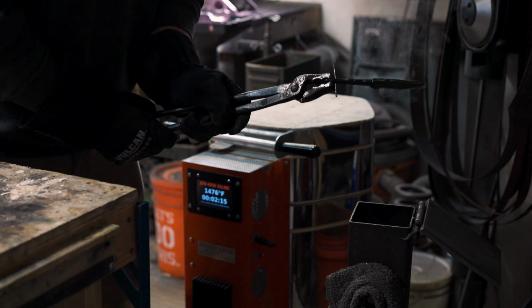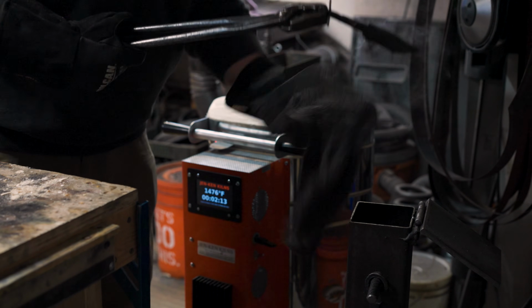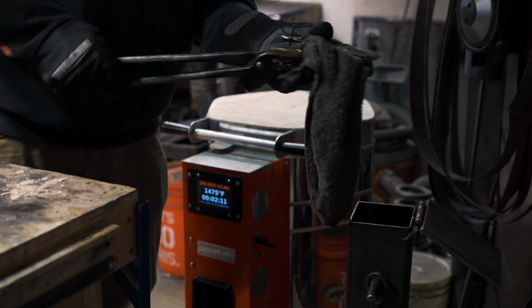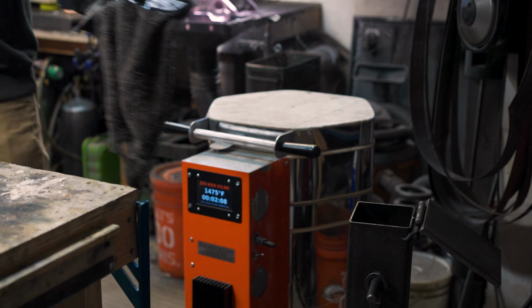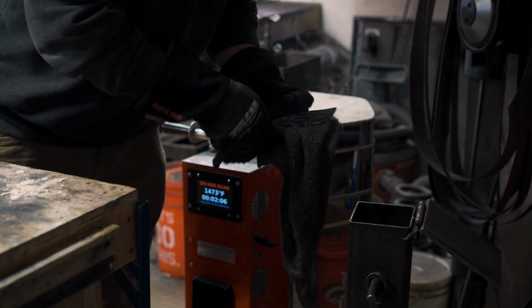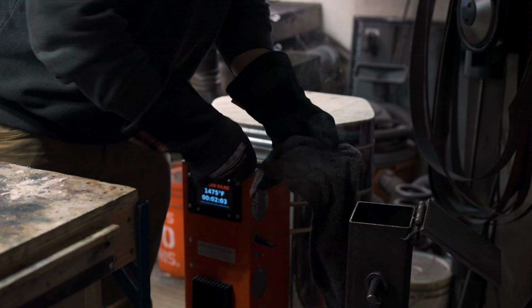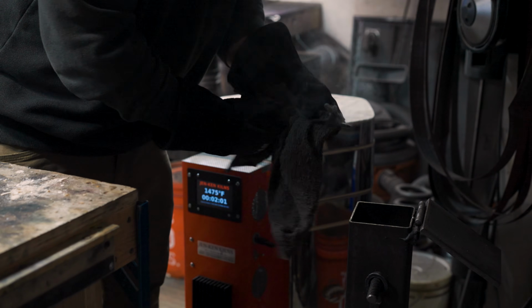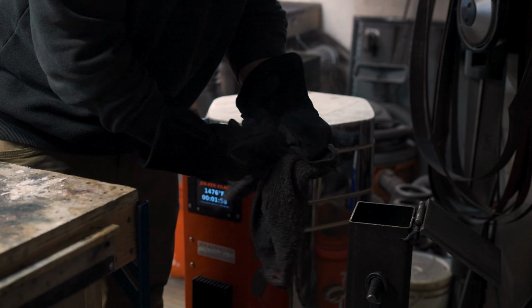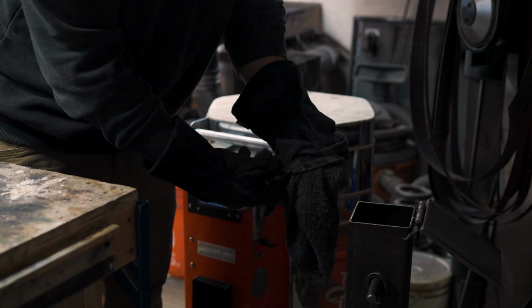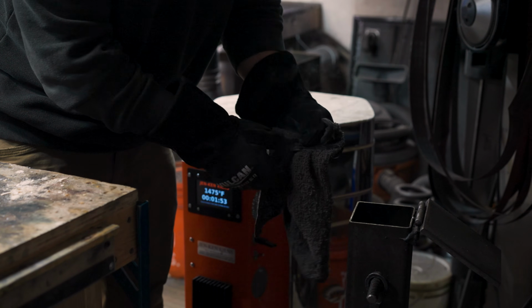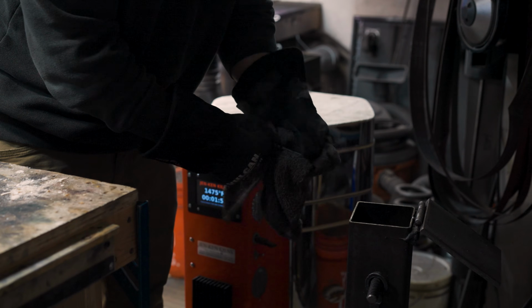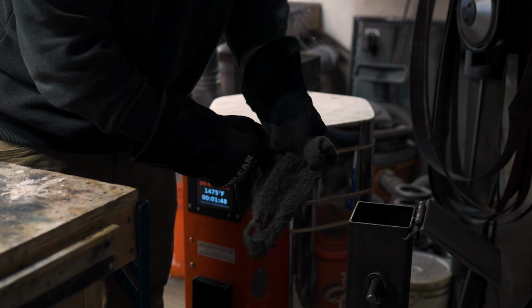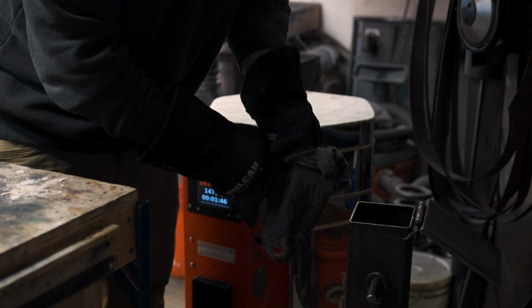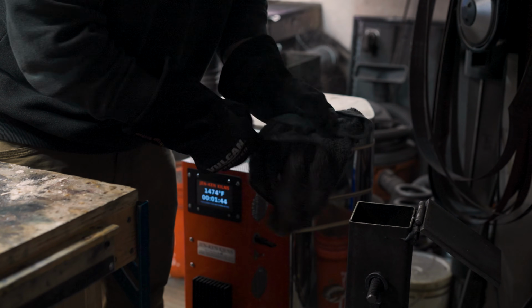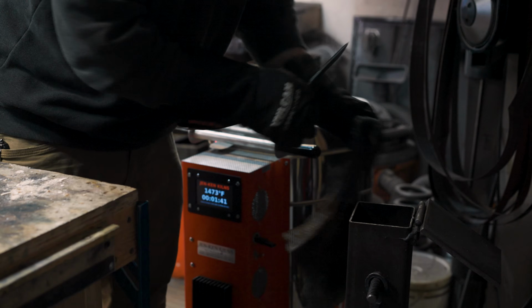So once I've quenched this, I like to grab it with the rag and wipe off the scale. It's one decent way to tell if you've gotten a good quench, if you get all this scale build up on here and it comes off really easily. It's not a 100% definite way of telling if you got a good quench or not, but be pretty hopeful when you see it.